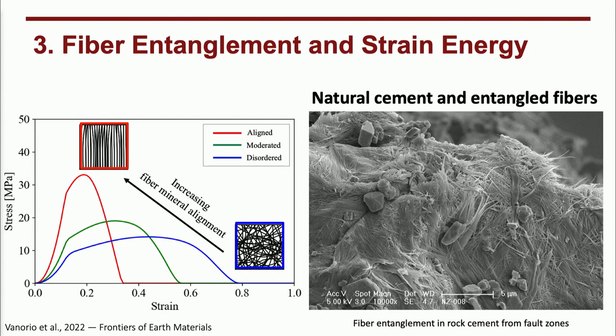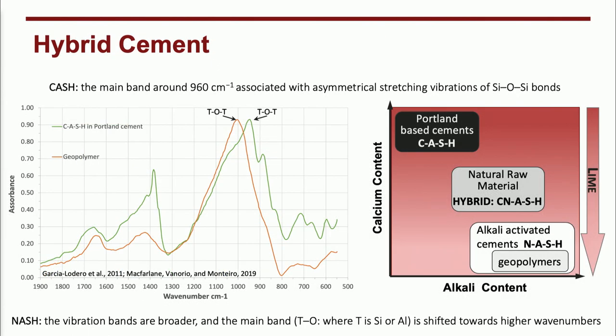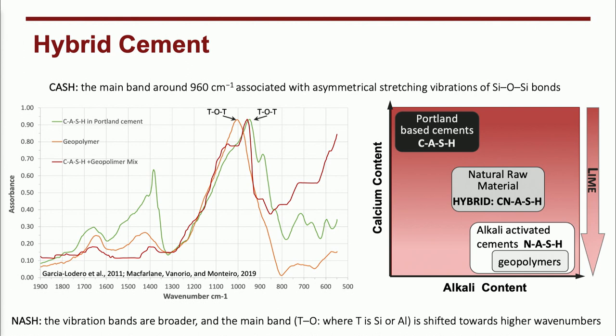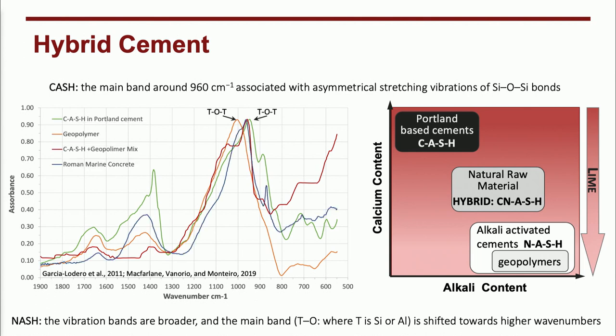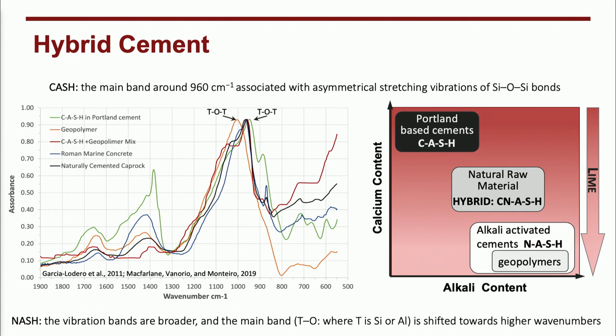If the fibers are straight, the stress is higher, but the strain is much smaller. So in order to get the same stress, you just need to use more fibers and grow more fibers into the material. At the end, our material is in between Portland cement based and alkali activated or geopolymer, so it's a hybrid composition. And in this plot here, you see the silicon-oxygen bonds. Normally, in a hybrid material, the FTIR response is in between. And interestingly enough, this is the same response that Roman marine concrete has. So Roman marine concrete is also a hybrid, like naturally cemented cap rocks that exhibit high strain absorbance.